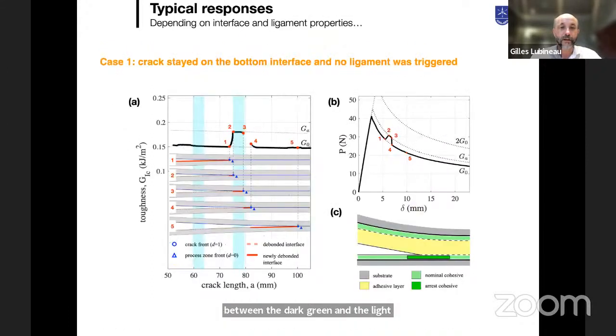So here, the first situation that can happen is that this is not going to modify anything. That means the contrast is not very big, and then you would get a classical delamination curve. The opening is going to be the same as usual. The crack is going to propagate at the interface, and when the crack reaches the tough region, locally the toughness is bigger, but you are not going to change any type of mechanism, and then the delamination is going to continue. So this is the first situation.